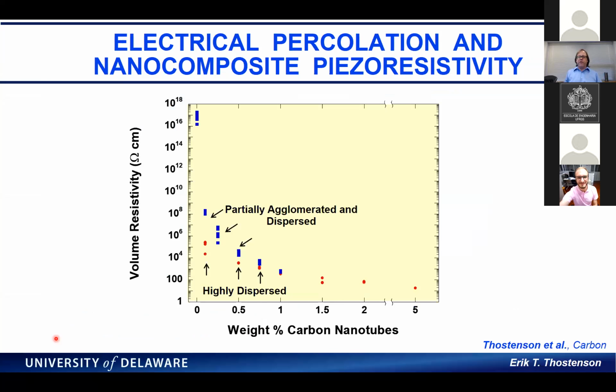So this is what really got me into looking at the sensing aspect: when we dispersed carbon nanotubes in an insulating polymer, we saw very low electrical percolation thresholds. The polymer itself is insulating, and these are two different manufacturing techniques that we use. But certainly what you see is that even at just 0.1 weight percent, we see several orders of magnitude change in the volume resistivity of the material.